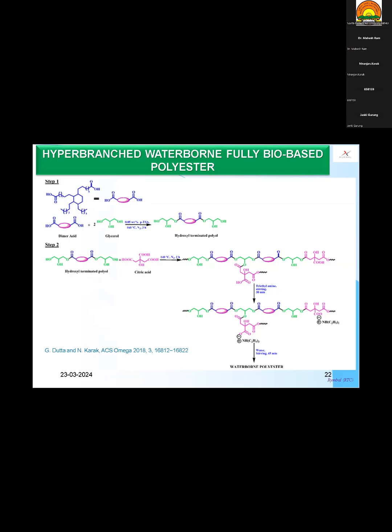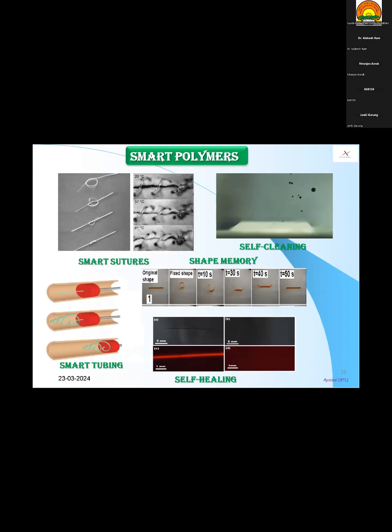In this endeavor, we have utilized dimer acid, glycerol, and citric acid, and produced a highly biodegradable waterborne polyester system from bio-based raw materials. Along with this, we thought, why can't we incorporate some special attributes into the polymeric system, obtained from bio-based resources and having special architectural features. So we have tried to synthesize some smart behaviors, some intelligent polymers. And because this can be utilized for different special applications, like say smart suture, where this will be required to be